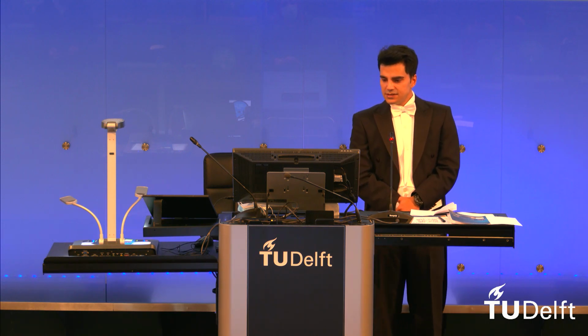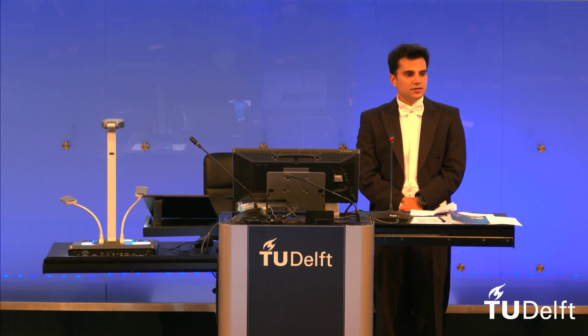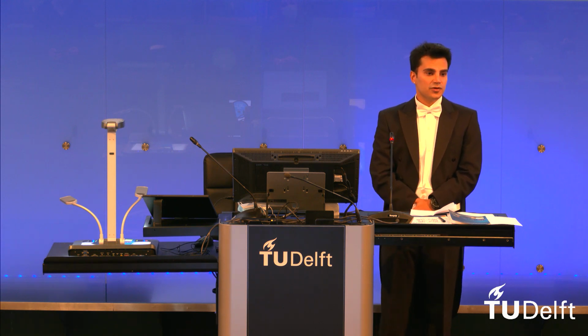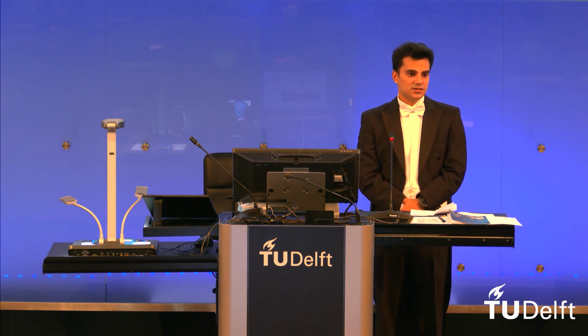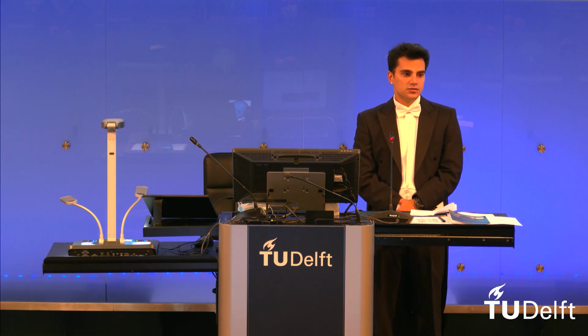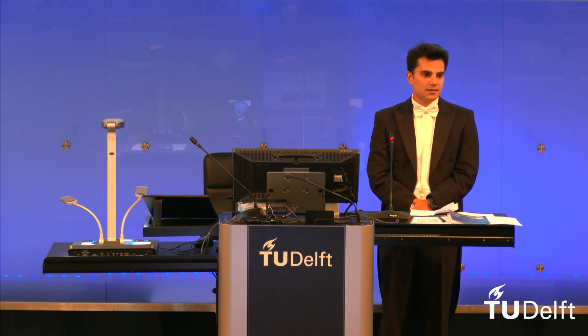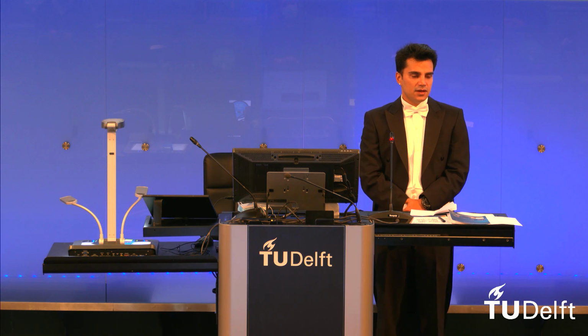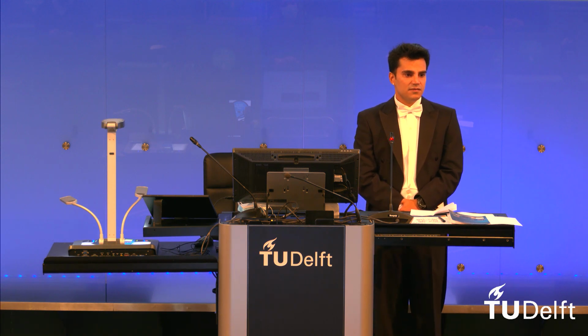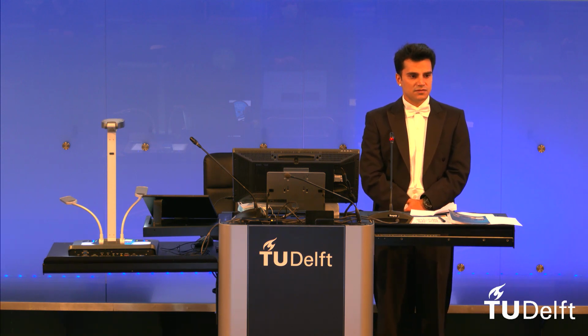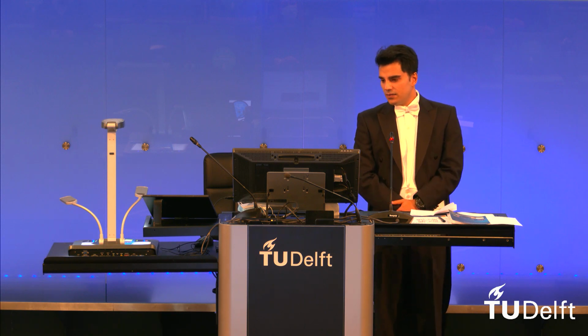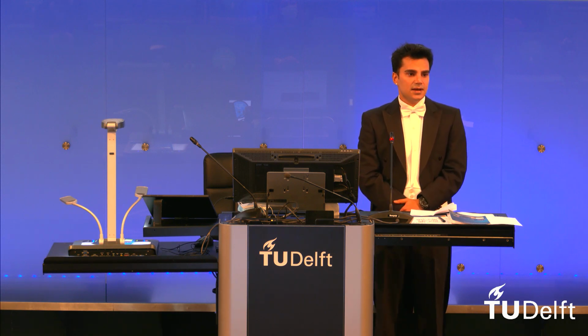It was also interesting to notice that after around 41,000 preliminary test revolutions, we were able to see potential corrugations in the test rig environment, which is quite interesting and also very unique in the current literature, that we have been able to produce such kind of defects, let's say potential defects, in the lab environment.